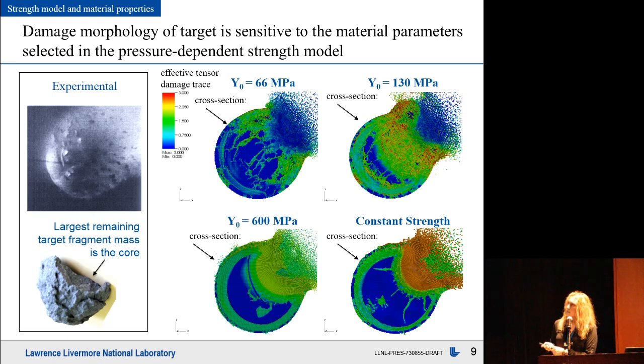It's only at 600 MPa that you start getting a large enough core to match the experimental results fairly well, and the same can be said for the constant strength model.